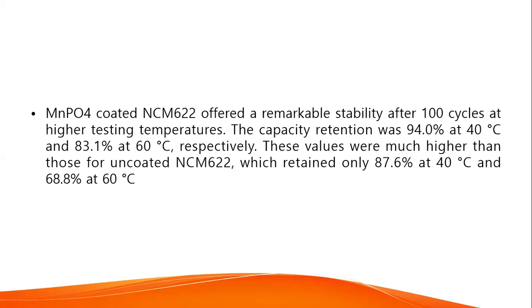MnPO4 coated NCM622 offered a remarkable stability after 100 cycles at higher testing temperatures. The capacity retention was 94% at 40 degrees centigrade and 83.1% at 60 degrees centigrade respectively. These values were much higher than those for uncoated NCM622, which retained only 87.6% at 40 degrees centigrade and 68.8% at 60 degrees centigrade.